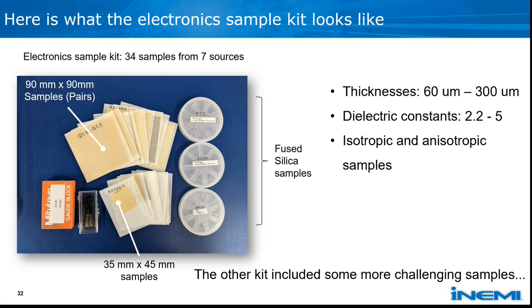Additionally, you can see on the left just sort of a photo of the sample kit. And we had all of our samples broken into either 35 by 45 millimeter coupons for some of the smaller measurement setups, and 90 by 90s for the Fabry-Perot and BCDR instruments.